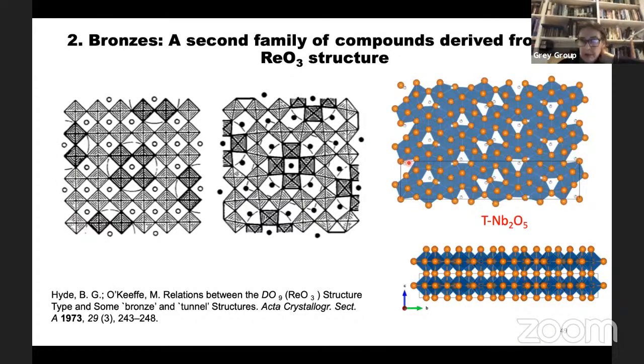The other way to do it is via so-called bronzes, and they're called bronzes because they have bronze-like colors, is to take 4 of these units and rotate them around. So this is the same unit here, but now I've rotated it by 45 degrees, and you can see then that you've got the 5-membered rings instead of these 4-membered rings, and you can form a structure called T-Nb2O5 that has this sort of bronze structure.